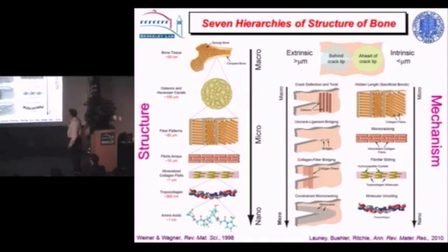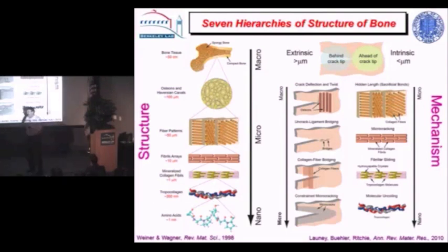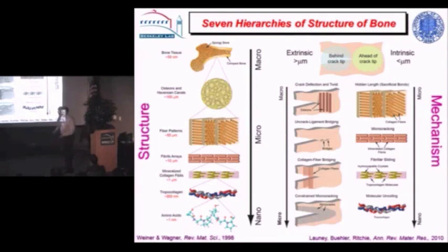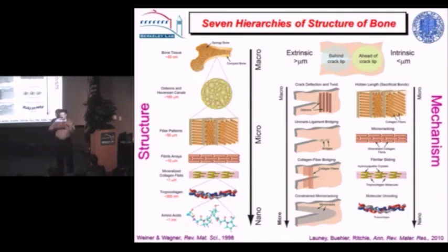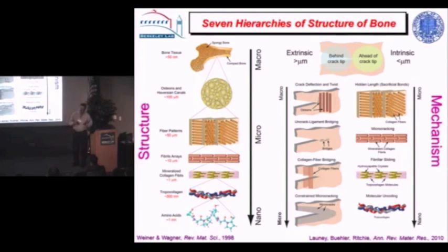Bone has this hierarchical structure from collagen and mineral fibrils up to Haversian canals and osteonal structures. We can identify toughening mechanisms at every one of these scales. Below about a micron, the processes are associated with intrinsic toughening — plasticity. Bone primarily derives its plasticity by sliding of mineralized collagen fibrils apart. This fibril sliding mechanism is the main source of intrinsic toughening and is affected by the cross-linking of those collagens. But an even bigger effect is the extrinsic effect associated with crack growth in bone.